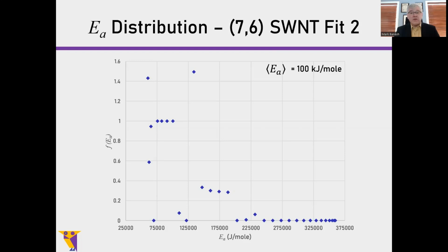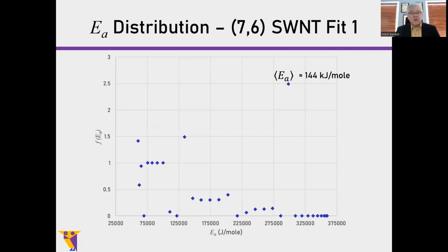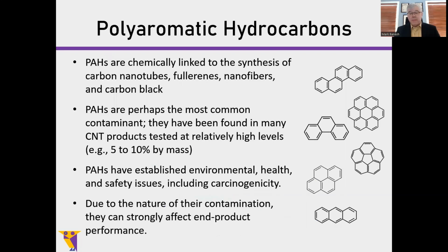This technique looks at a true distribution function, and we can see that we have a range of distributed values. And that's interesting because this is clearly not a homogeneous surface, nor is the other fit component. They have similar distributions, but they do not have a delta function. This is advertised as a highly pure, again, highly NIST certified material, and yet its surface is not homogeneous.